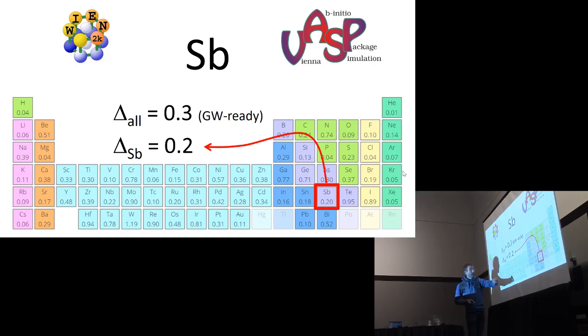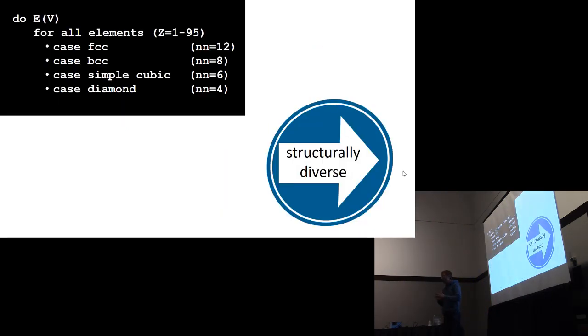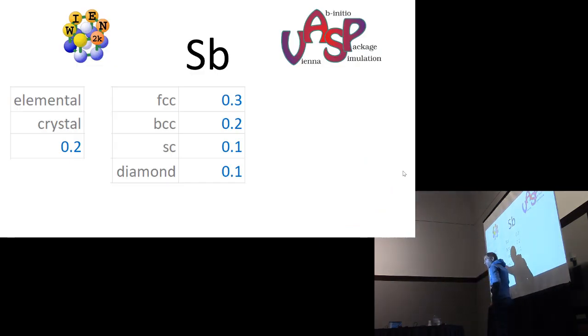With all these guidelines in mind, we try to increase that test set. I will illustrate by one element, antimony, which had in the WIEN2K VASP comparison a delta value of 0.20, how that larger test set can look like. Having more structurally diverse antimony crystals, that's straightforward to do. You can just go through FCC, BCC, cubic diamond crystals to scan the different types of coordination from 12-fold coordinated to 4-fold coordinated. That's a good measure of structural diversity. So four different antimony crystals in this crystal structure. If you would do that for antimony, delta value of 0.2, in these four crystals it gives you very comparable numbers. So the conclusion that you reach here is carried over to the more structurally diverse crystals.